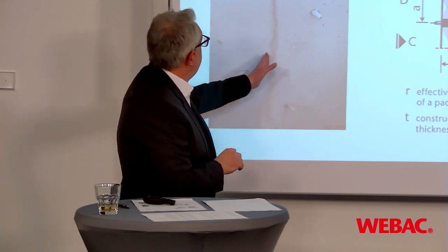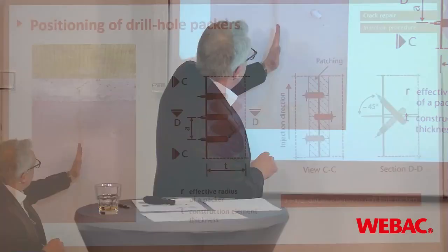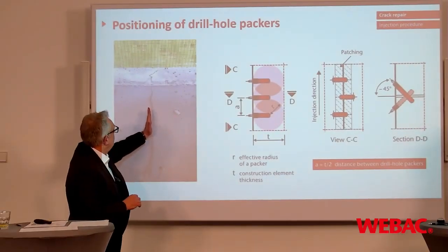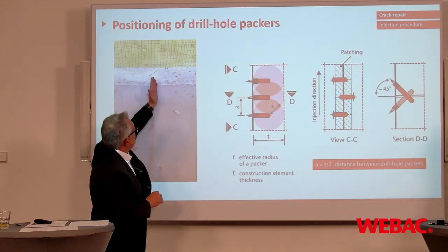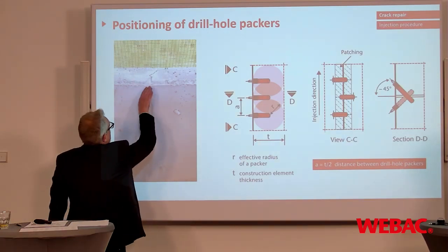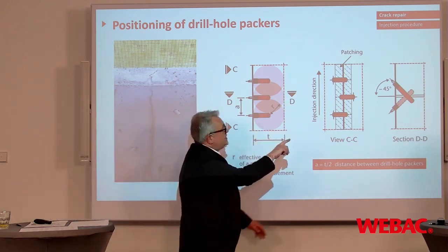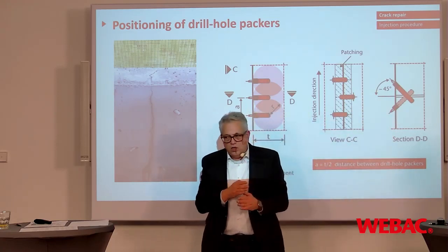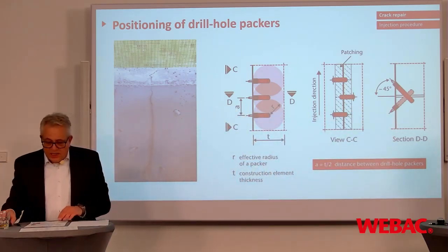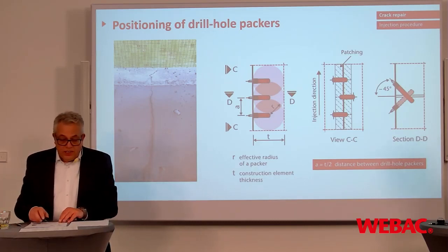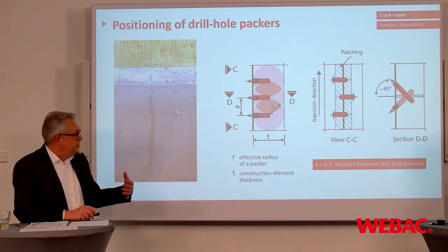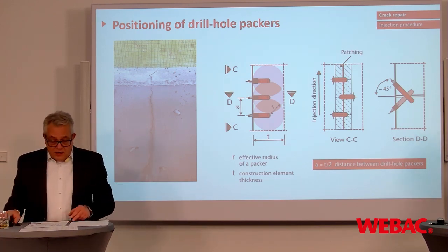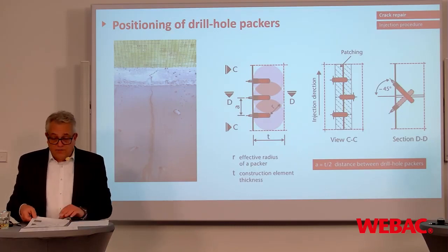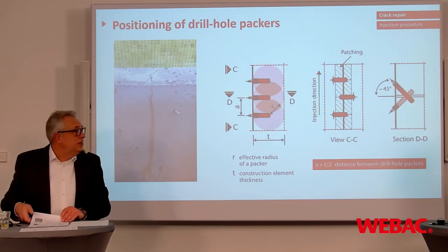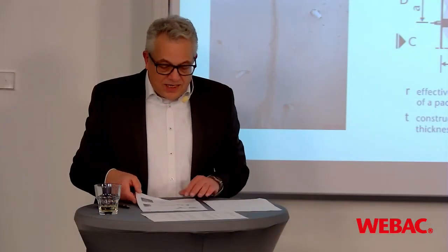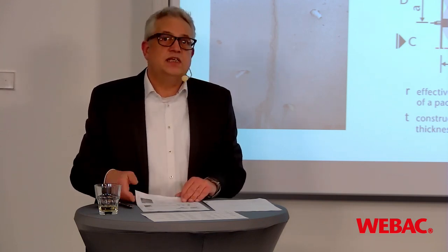I hope you can see this picture here. The reason is that if you are standing in front of the crack, you will never know how this crack went in the construction. In this case, it goes to the right side. And with this angle of 45 degrees, you ensure that you intersect the crack. That is the reason for the angle of 45 degrees. So, distance, in general, you can say half of the construction thickness. If you now have a slab which is 1.80 meters, you will probably not drill 90 centimeters into the concrete, but this has to be seen case by case.